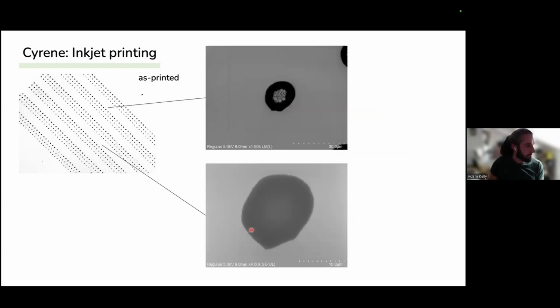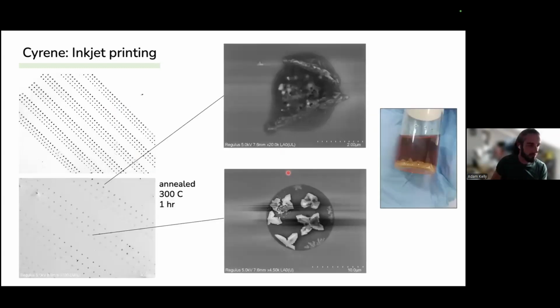We then printed this material onto silicon dioxide. We found some kind of coffee staining effect, but that can probably be resolved by tuning the surface energy by treating the surface of the silicon dioxide. The problem is Cyrene is a high boiling point solvent. The boiling point, as we saw, was about 200 degrees. So to remove the solvent, we performed annealing at 300 degrees.